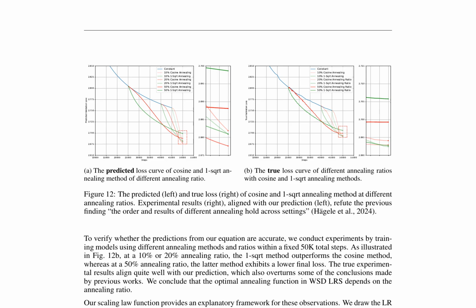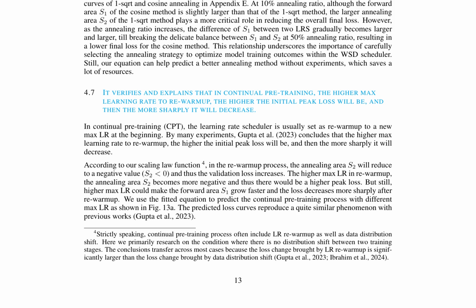Our equation demonstrates that the validation loss can be predicted by analyzing the forward area and annealing area of the learning rate curve. The forward area, which corresponds to the initial learning phase, primarily influences the final model performance. In contrast, the annealing area, associated with the learning rate decay phase, has a smaller impact on the final loss. We apply our equation to explore the relationship between annealing methods and ratios. The results indicate that at a 10% or 20% annealing ratio, the 1-SQRT method outperforms the cosine method, while at a 50% annealing ratio, the cosine method exhibits a lower final loss.